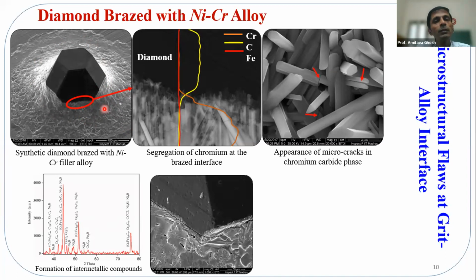I didn't mention, but because there is an active element, you need to have this brazing realized under a very high level of vacuum. This level of vacuum is 10 to the power minus 8 to 10 to the power minus 9 atmospheric pressure. So as I said, that non-coherency and the typically very high hardness of the chromium carbide, caused by the residual stress, receives a crack.